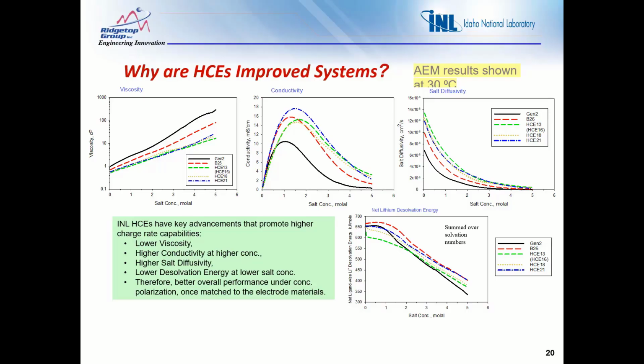So in our cases, we've developed a suite of what we call HCEs, highly concentrated electrolytes, that can be designed and tailored toward particular materials. In our fast charge program for DOE, they're using thick electrodes. These are approaching 80 micron laminate thickness for both cathode and anode. That is a very challenging set of requirements to maintain fast charge conditions when you have that kind of thick electrode structure for the electrolyte to work within.